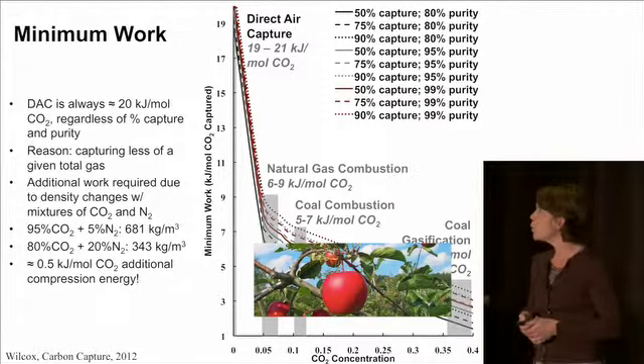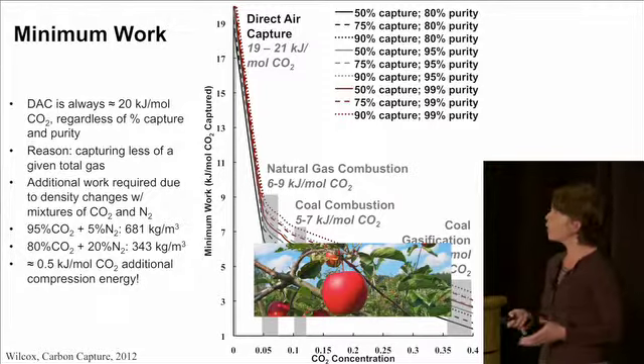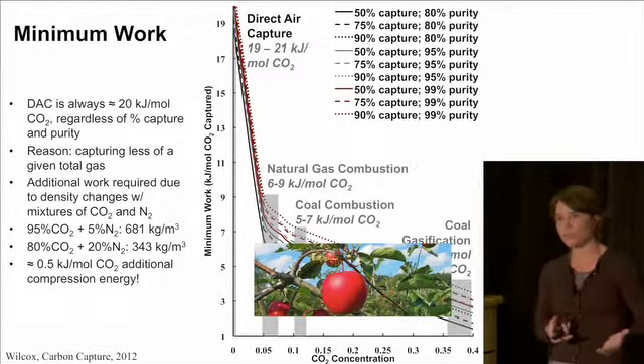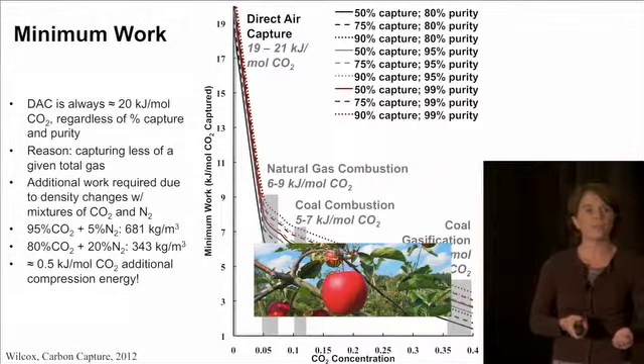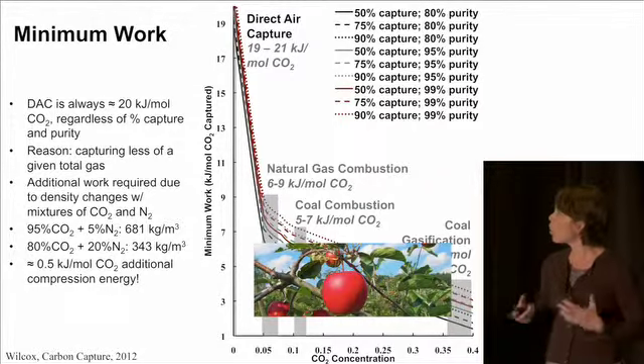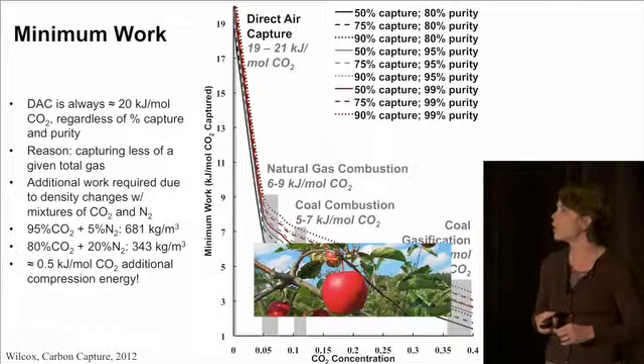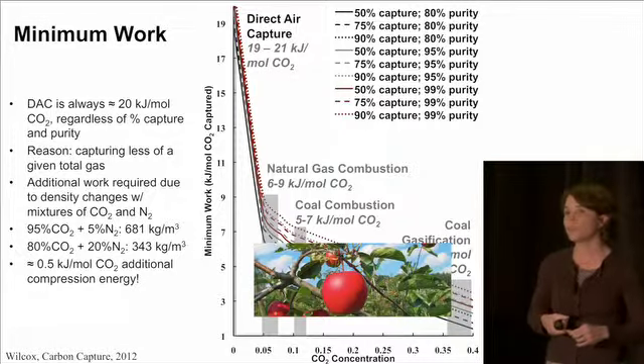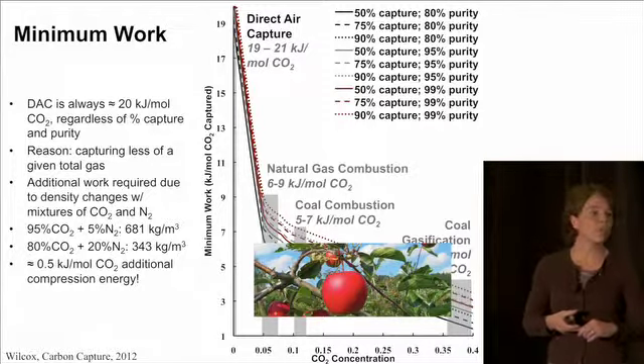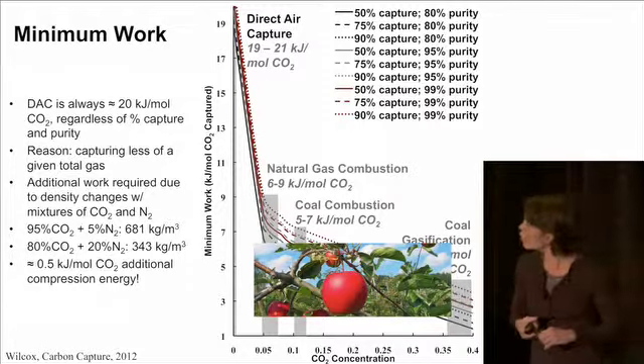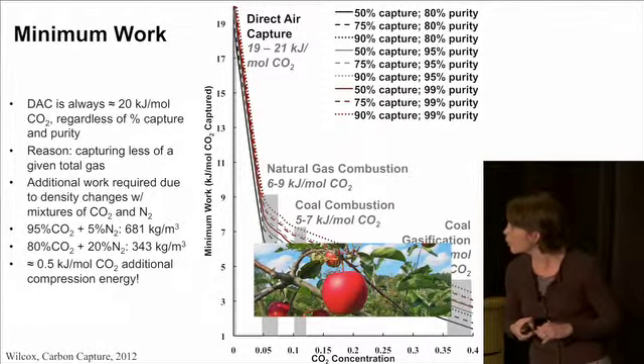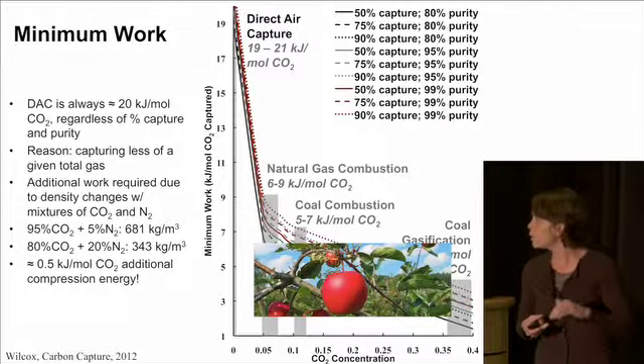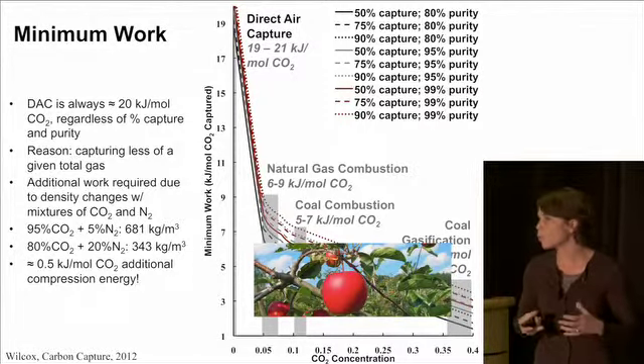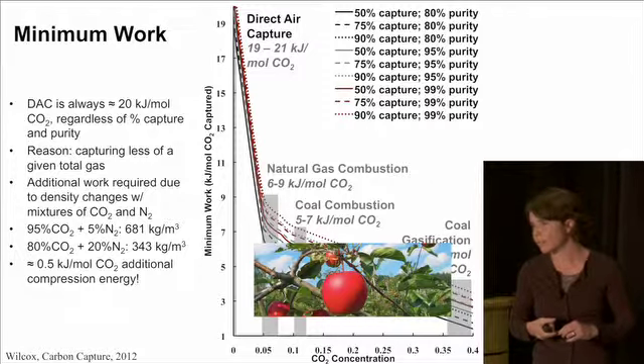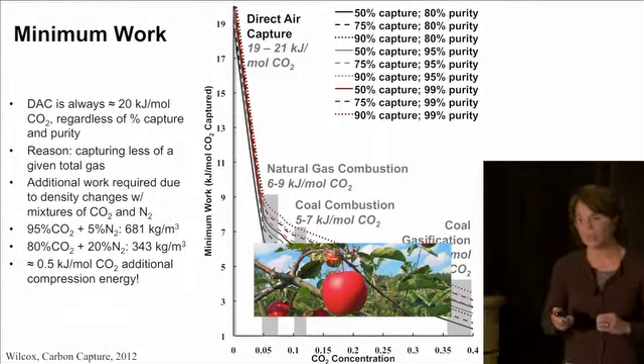One thing I also want to mention here is that I've looked at a range of percent capture versus percent CO2 purity. And what you find is that in the case of compromising on the purity, you have to be careful because the densities of these gases change significantly. If you have to compress and transport CO2 in a pipeline, going from 80% CO2 up to 95% CO2 is a significant increase in density. So there's going to be less work required if your gas is in a more dense state. So you have to be careful when you compromise on that dilution.